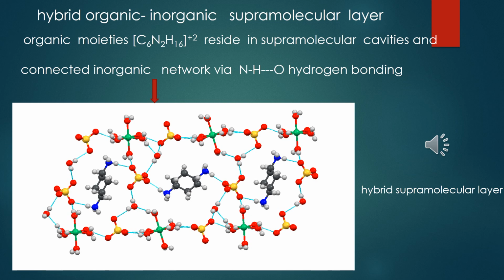The organic building block trans-diaminocyclohexane, protonated, resides in the supramolecular cavities and is connected to the inorganic network via N-H...O hydrogen bonding, giving rise to the hybrid supramolecular layer.